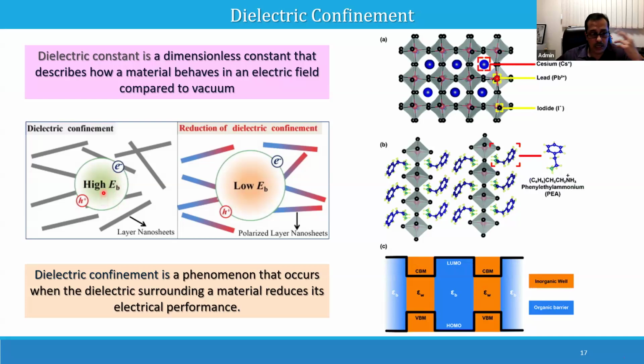So they are very close to each other. So the interaction between the electron and hole is very, very high, and that will result in high exciton binding energy. Try to understand the term exciton binding energy. Exciton means the electron and hole pair, and the energy of that binding is very high. And if the exciton binding energy is very high, the dissociation of the exciton is difficult. That is so obvious, isn't it? So the exciton binding energy is high, and the dissociation becomes very difficult. That is why we are not able to get good efficiency or good performance with this lead-free material.